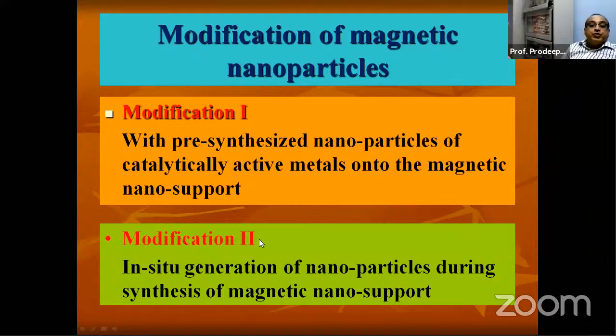Secondly, modification 2: in situ generation of the nanoparticles during the synthesis of the magnetic support. So what happens here? You take the magnetic nanosupport as well as this catalytically active material, these compounds, then you combine both and generate nanoparticles during the synthesis of the nanosupport.